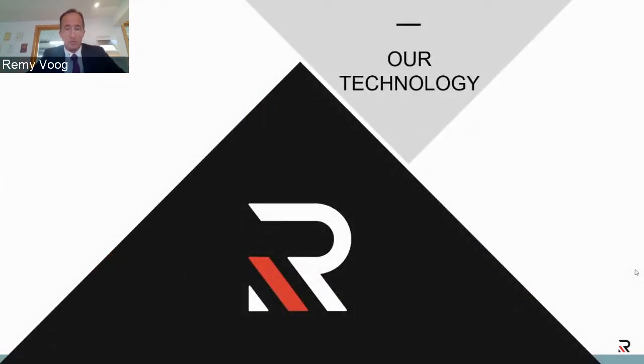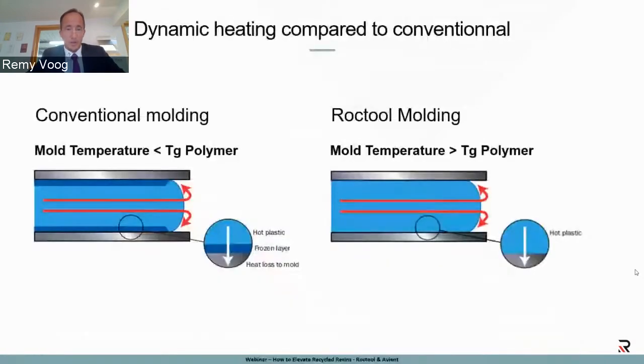Now a small focus on how the technology works. On the left side, you've got a conventional mold, and on the right side, you've got a Roctool mold. In a conventional mold, you will have a hot resin, which will arrive on a cold molding surface. What's going to be created is a frozen layer, and this frozen layer is the source of some of the issues that you may face in injection thermoplastics. Some of them are aesthetic: weld lines, sink marks, fiber visible at the surface.